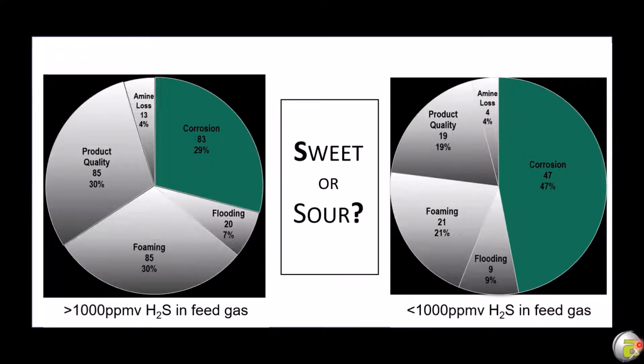And the huge reason for that is that H2S, although it corrodes steel, it does form a protective film we call iron sulfide. And as you process relatively high H2S gas, you build a nice protective film in all the equipment and piping. And over time, this reduces the corrosion potential of your system. In a CO2 environment, the CO2 or the iron carbonate doesn't form a protective film to any great extent in amine service. So the CO2 can continually attack the steel, and it tends to form pitting corrosion, which is a lot more aggressive and a lot more dangerous to operations, because we can punch holes in the side of vessels with CO2.